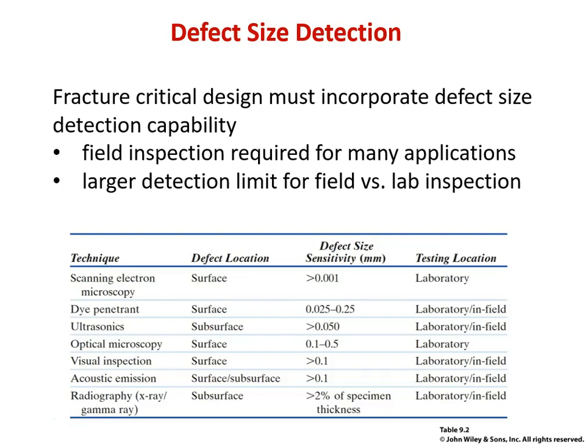And then radiographic, which is x-rays, sometimes gamma ray transmission. And that's obviously subsurface, and it can be anywhere around 2% of the specimen thickness. And again, that's obviously much better for small parts that can go through a radiographic facility, not so good for the field, but could be very valuable for a manufacturing scenario.